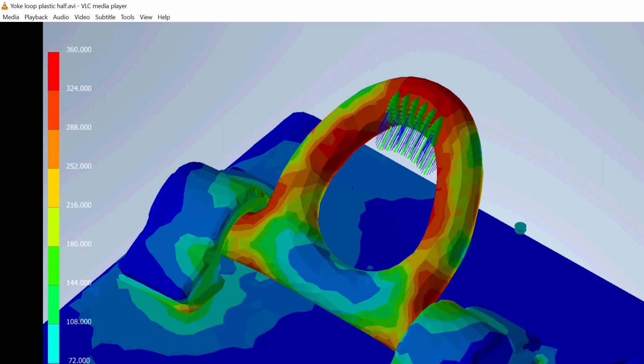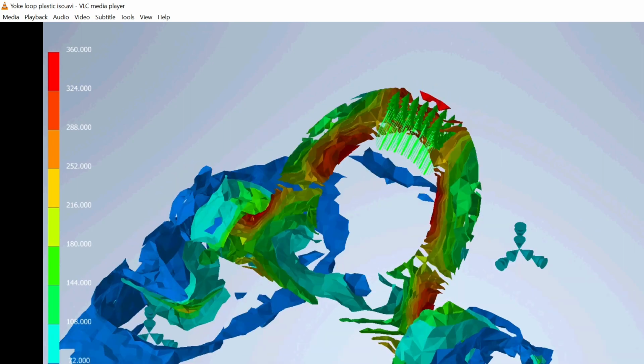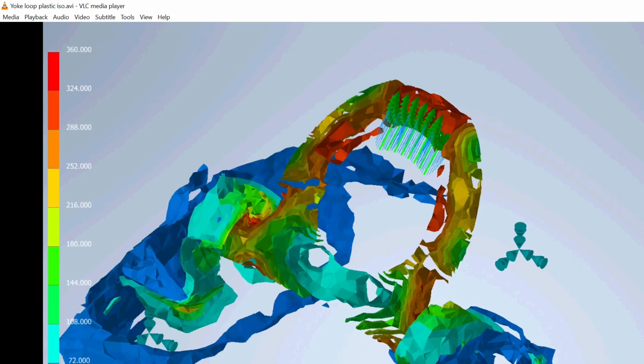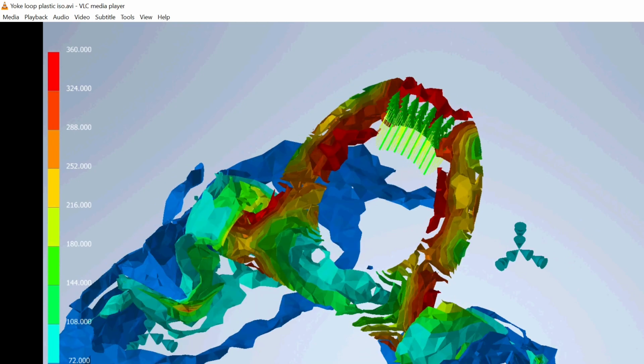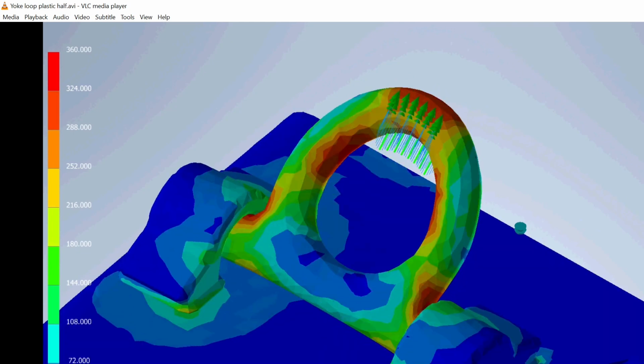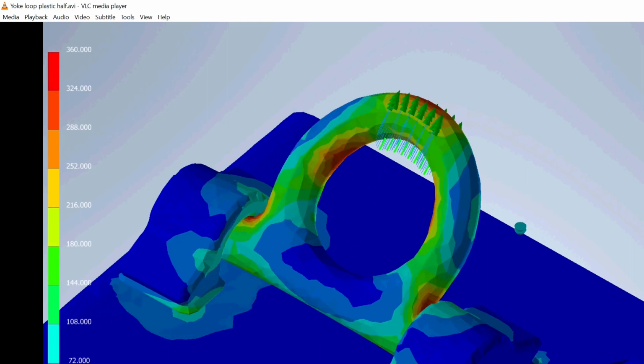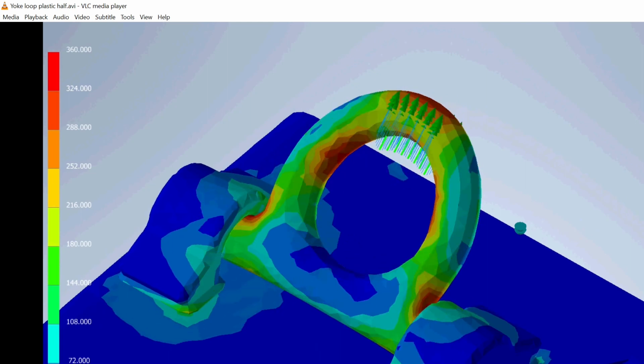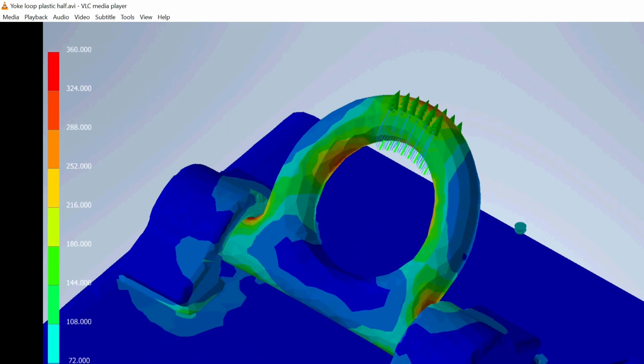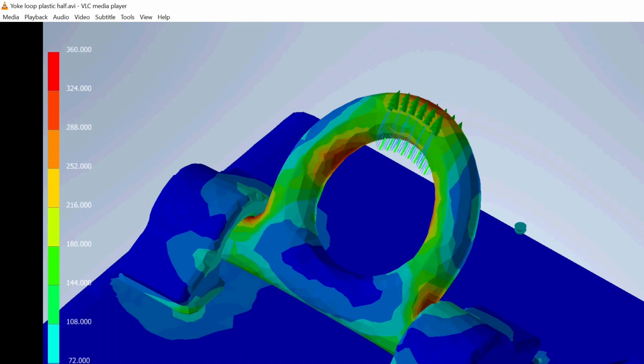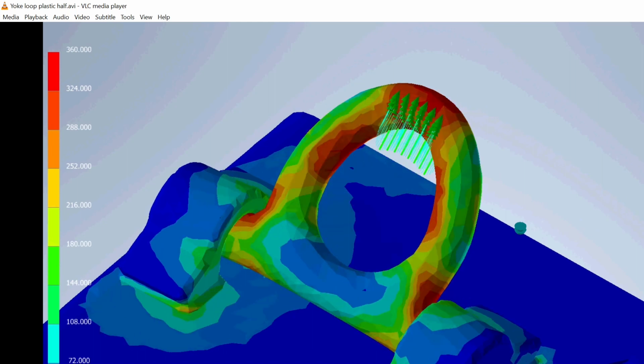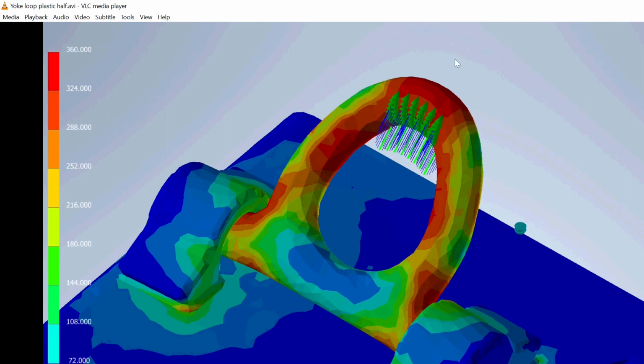And with all of these deformations and advanced simulation mode in NAstran expansion package, you can even see the residual stresses. And that also gives you an idea of how different the plasticity and elastic predictions are. The elastic prediction says that this part can hold approximately half of the load at 50%. That's where the limits begin to get triggered, and that would not pass. If you have a plastic simulation, the stresses redistribute, and you can find that the actual structural failure happens around twice the load.